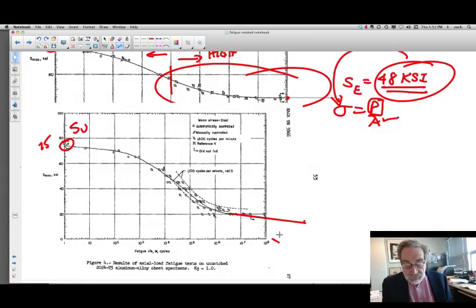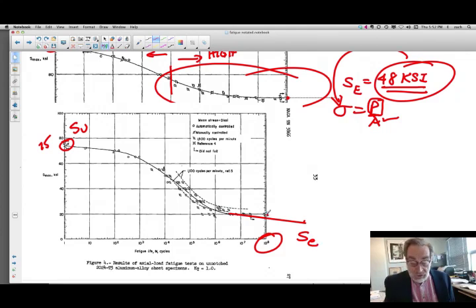We'll still give an endurance limit. But we understand that if we want more than that, we're going to have to use more life than that. We're going to have to use even smaller stress. So we're down in here on the order of, this is 10, 15, like it's only like 17 ksi. It's pretty small where the ultimate strength of this thing is 75 ksi.